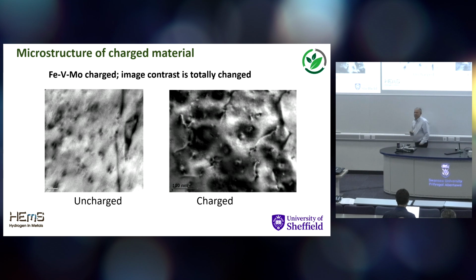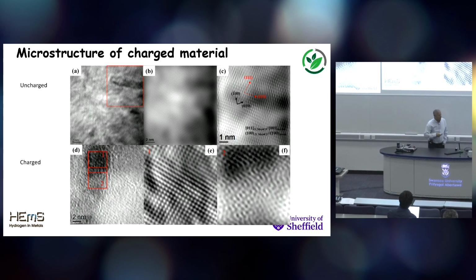In addition, we modify the precipitate strain field. So on the left here, TEM image uncharged. On the right, after charging, you can see the strain field now looks really rather different than the sort of classical strain field that we see on the left. This rather enlarged strain field on the right actually leads to an increase in residual strain in the material before you've done anything other than just charge it with hydrogen. I think that's shown again in this image here, high resolution image of the precipitate, uncharged at the top. You can see the precipitates there, you can see the coherent nature of them. When you try and do the same imaging after it's been charged, precipitates here, and you really can't form a decent image within the matrix around it because of this strain.